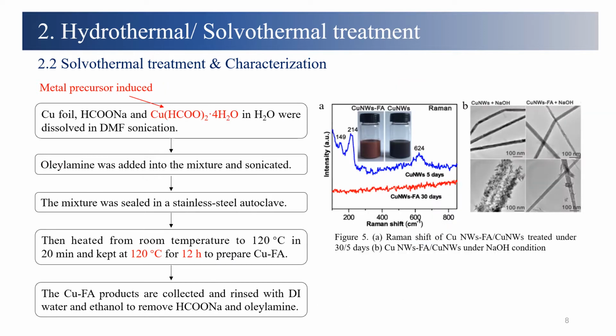However, the previous slide showed the solvothermal treatment without metal precursor. After introducing the metal precursor, the reaction temperature can be reduced to 120 Celsius. This method can also be used in nanomaterials, like copper nanowires. From Figure 5, we can see the treated nanowires also showed good anti-corrosion properties.